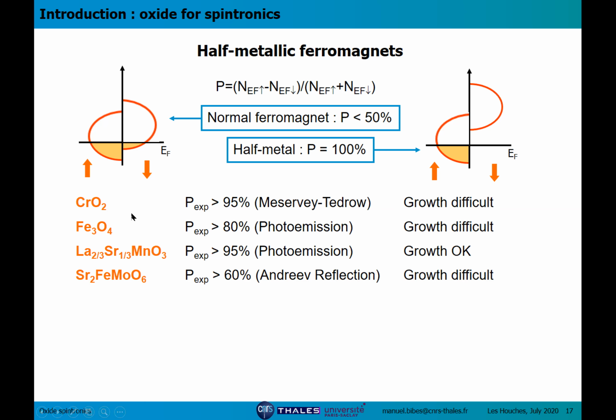Chromium oxide has a TC of about 400 Kelvin. It is quite difficult to grow because the most stable valence of chromium is 3+, and here you want to have chromium 4+, so it's not very easy to make. But measurements showed a very large value of spin polarization, about 95%.